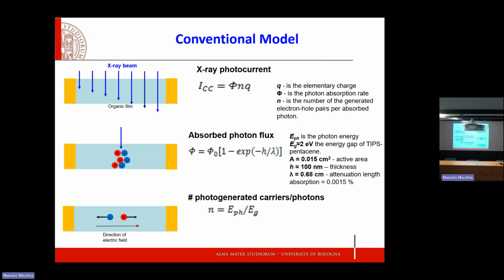So the collected photocurrent is provided by the product of the elementary charge, the photon absorption rate, and the number of generated pairs. But how many photons can be absorbed? Let's try to estimate the absorbed photon flux. And we need to do this calculation to know the energy gap of pentacene. It's about 2 electron volts, so very similar to inorganic semiconductors. The active area, the thickness, 100 nanometer, and the attenuation length. That gives us an absorption which is ridiculously low. Look at that. The number of photogenerated carriers and therefore of the collected current should be less than 2 picoamps. So this model is not providing us an explanation of why we are measuring tens of nanoamps in practice.